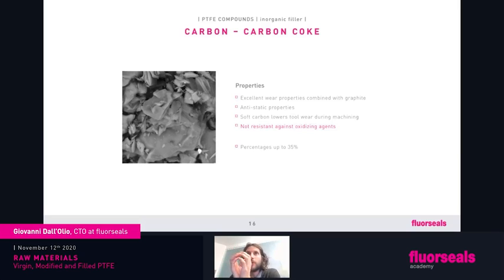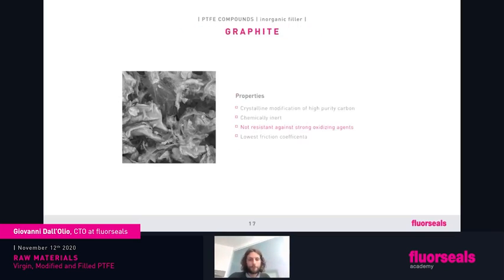Soft carbon, that is a more expensive kind of the shape of the carbon itself, will help a lot, mainly on the machining, because it being kind of softer during the machining, you will wear less the tool. So if we have to produce a very big batch, and the tool wear of the machining can be a problem, because we do have to change the tool, then the setting of the machine is different, then the tool has some cost. Sometimes it's better to use soft carbon, for example. It has some weakness about oxidizing agents, but that's not the main issue. On carbon, the common percentage is 20-25, but we can produce up to 35% of filler.